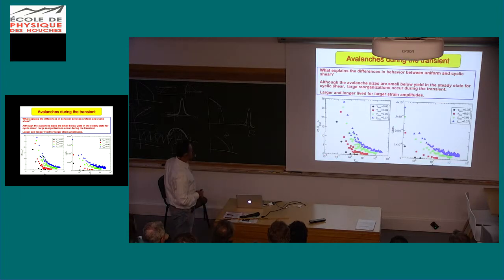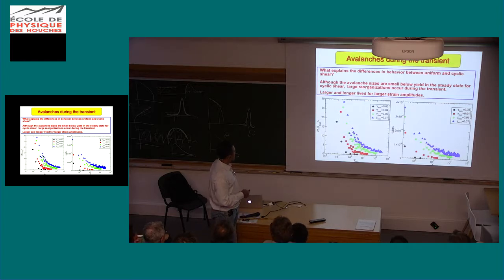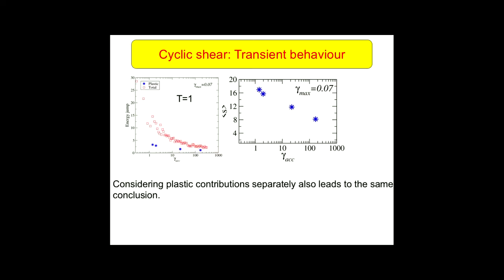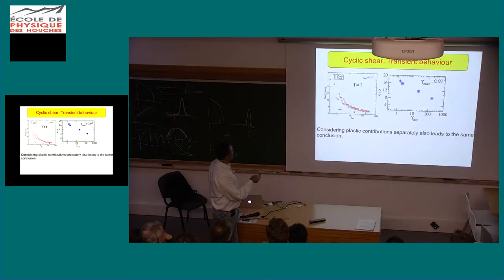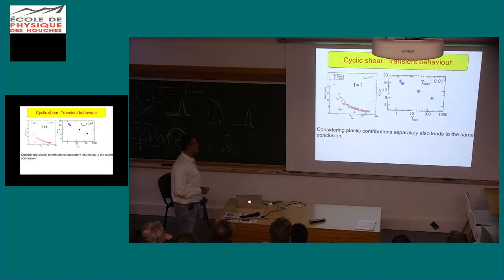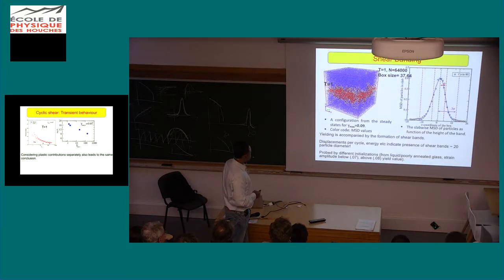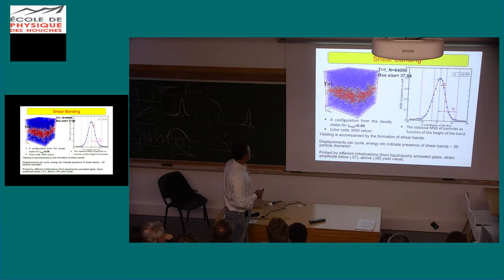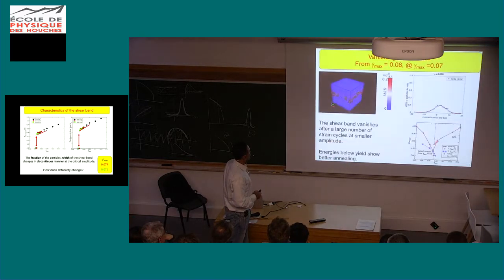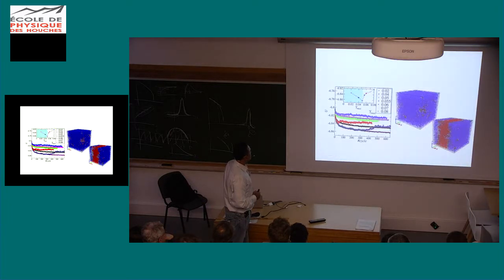And the quick answer to that is, as you strain cyclically the glass, the energy drops decrease with the cycle, and so do the stress drops, and we can also separate the energy jumps between the plastic and the total, and also look at the sizes of the events that correspond to them, and these are basically decreasing as the system gets annealed. This I will not cover because I don't have time, and it wasn't actually the part that I had in mind to talk about.